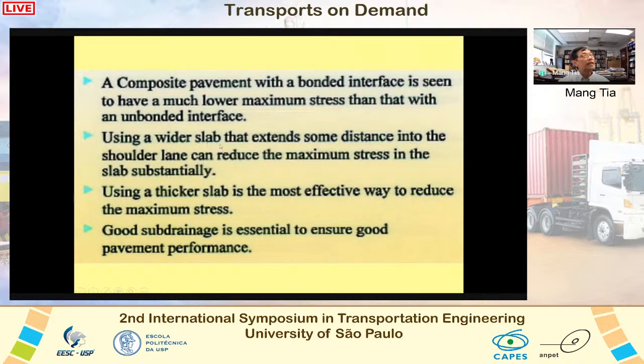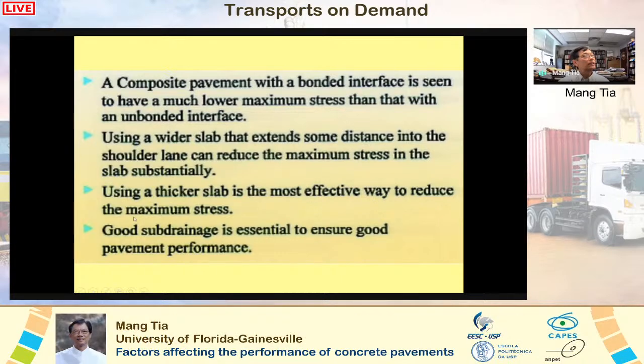Using a wider slab that extends some distance into the shoulder lane can reduce the maximum stress in the slab substantially. Using a thicker slab is the most effective way to reduce the maximum stress. And as most people already know, good subdrainage is essential to ensure good pavement performance.